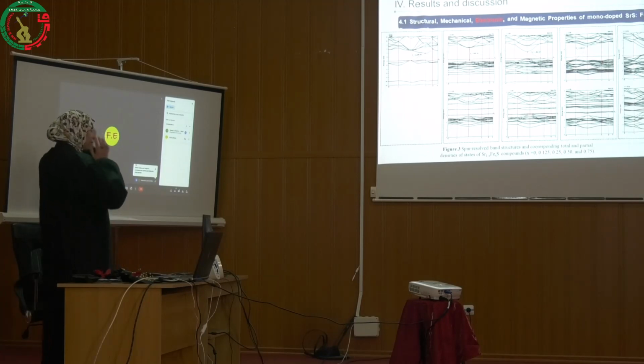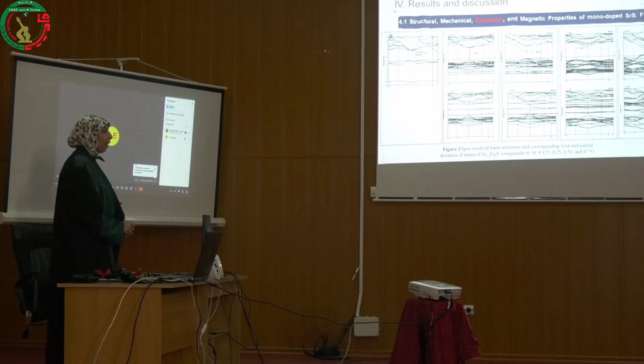The electronic properties are calculated in terms of band structures and total and partial densities of states. From this figure, it is evident that the binary SrS has an indirect wide band gap in the Gamma-X direction. After doping iron, the behavior transitions to half metallic ferromagnetic, with a direct band gap for 12.5% iron and an indirect band gap for 25-50% iron, and a metallic character for 75% iron.